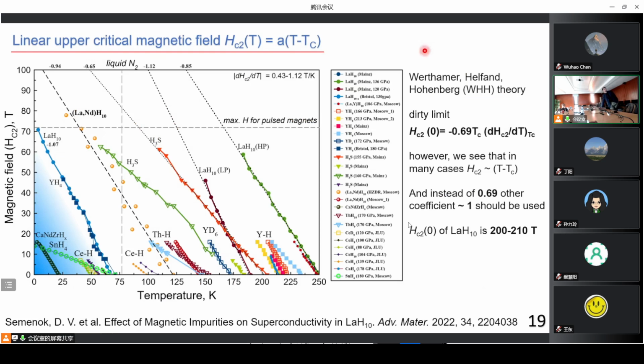You can see I collected the data for all hydrides, and this plot is published in a recent paper in 2022. We published in Advanced Materials. You see that for almost all hydrides, the known part of the magnetic phase diagram is linear, but it was predicted that it should not be linear. It should have a flat part according to the conventional Werthamer-Helfand-Hohenberg model. So it means that we, in fact, should increase the estimation for the upper critical magnetic field at 0 kelvins and change this coefficient 0.69 to 1. And it means that the upper critical magnetic field of many hydrides may be much higher than we thought before.